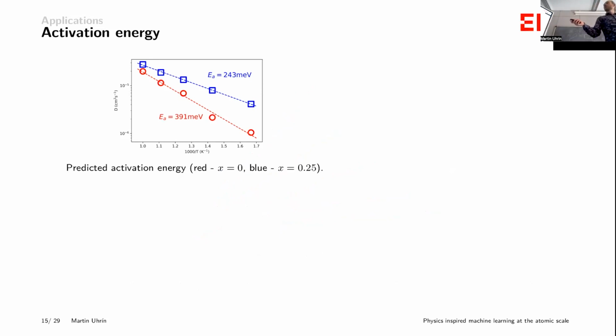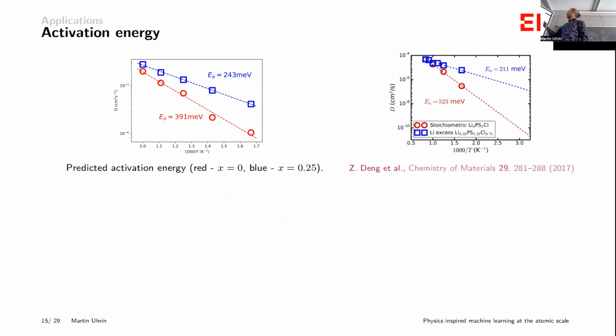So he's showing two different lithium concentrations: the pure, let's say the standard compound, and then one that's been slightly lithiated. And then we plot these Arrhenius plots, which allow us to extrapolate the activation energy for the lithium diffusing around in the lattice. We then dug up some literature and found that for both of our values, for the two different systems, we're actually not that far off, which is already quite an achievement. It's not that easy to get numbers that in absolute terms are in strong agreement with experiment. Often we're happy with, even if just the order and the relative numbers are good.